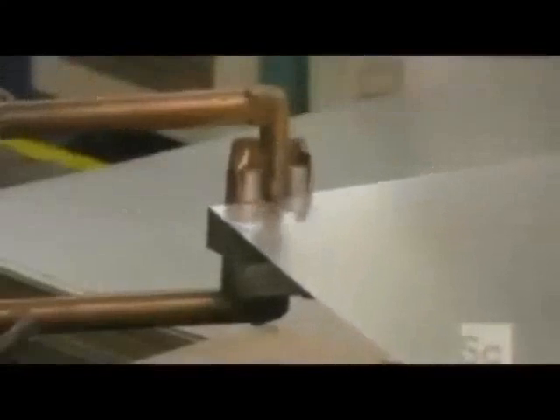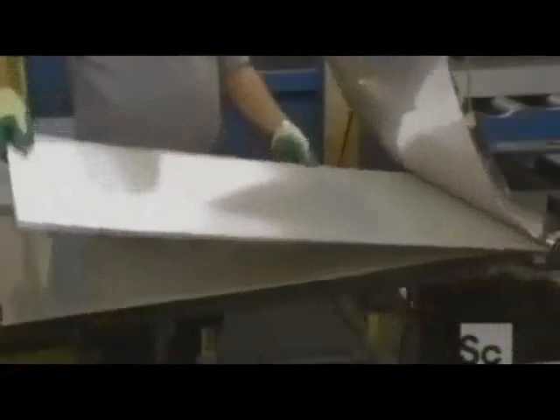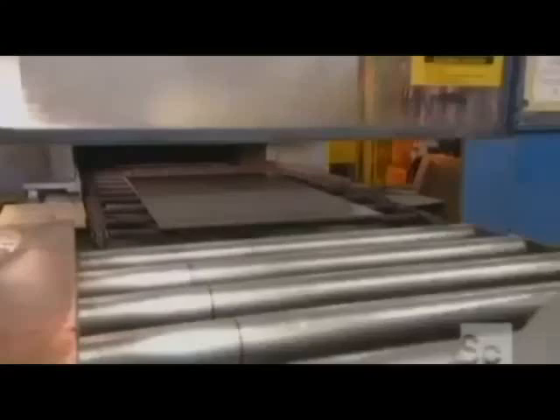Production begins with two stainless steel sheets. Using a spot welder, workers tack them together along one side. Then they lay the connected sheets onto an assembly fixture. A vacuum arm pulls up the top sheet, and they insert an aluminum sheet in between. This metal sandwich goes onto a conveyor that takes it on a 10-minute ride through an oven. The heat, 700 degrees Fahrenheit, softens the metal. This preps them for the bonding and shaping operations to come.